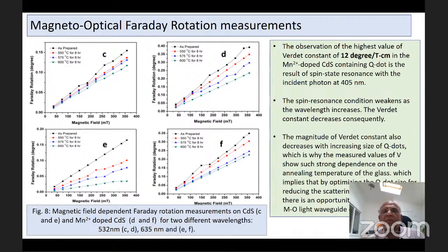As we are moving away from the band gap of the semiconductor, the spin resonance basically starts weakening, and as a result the Faraday constant also starts decreasing. The magnitude of the Faraday constant also decreases with the increasing size of the quantum dot because the band gap shifts to longer wavelength, which is why the measured values of the Faraday constant show strong dependence on the annealing temperature. This is quite important because by controlling the annealing, we can control the particle size and also the light scattering.